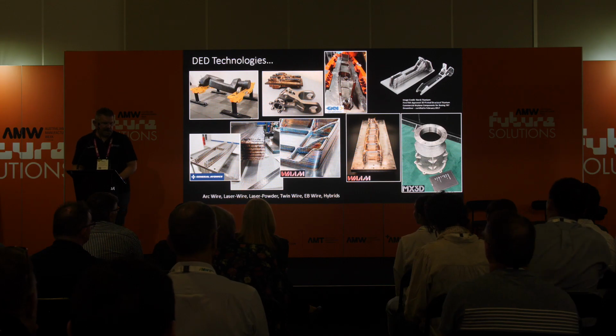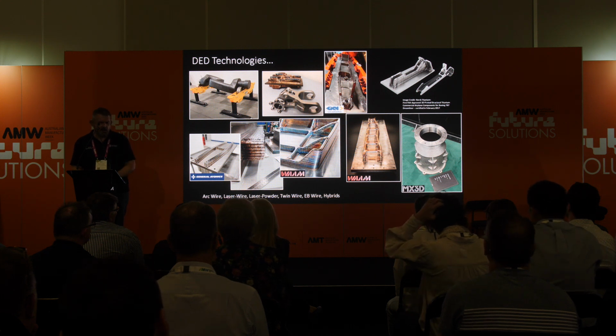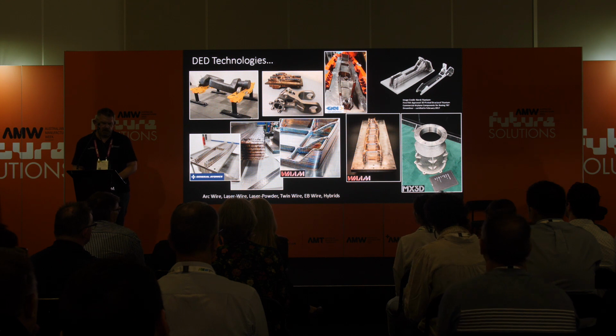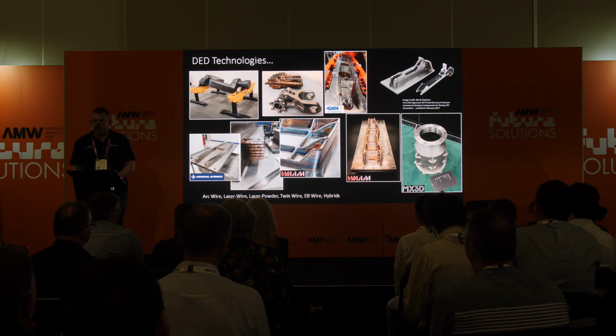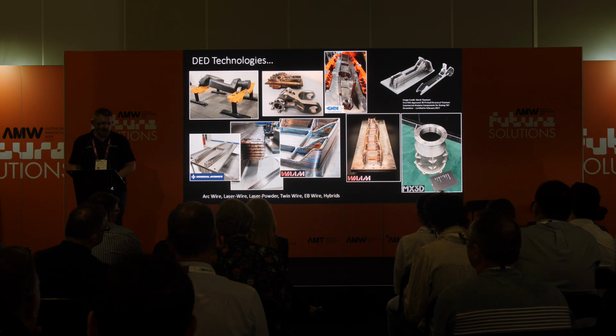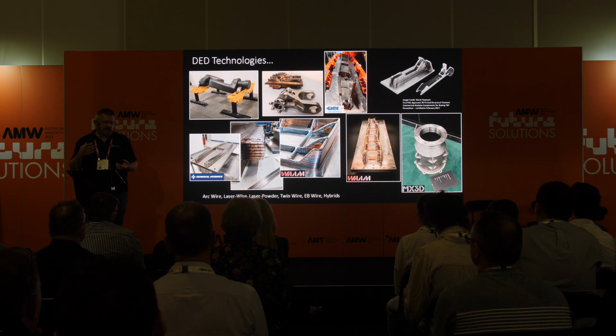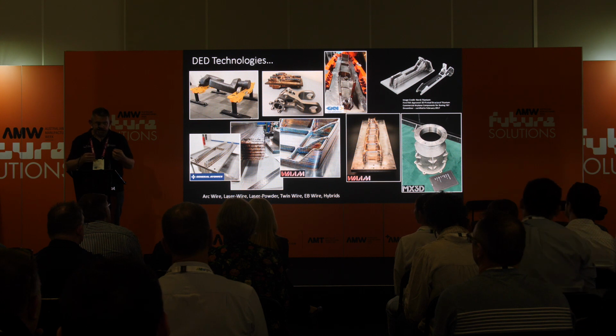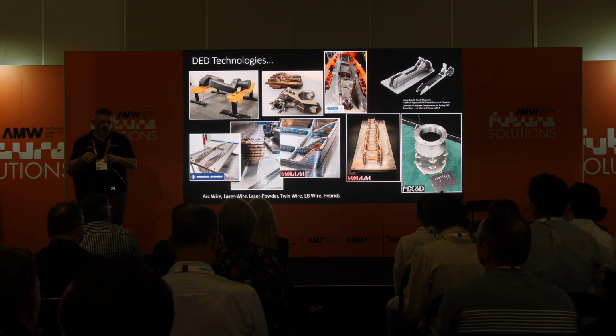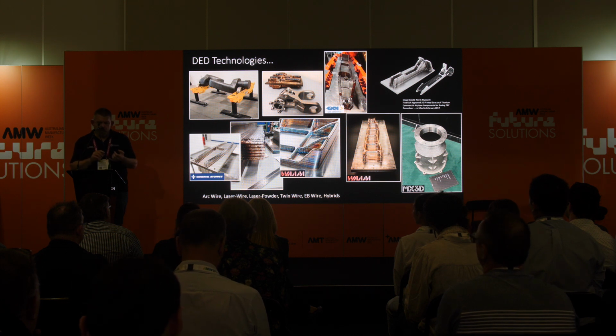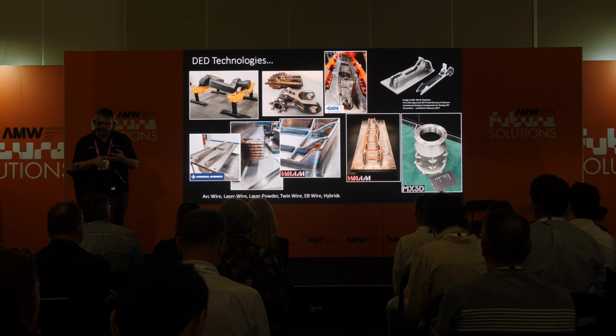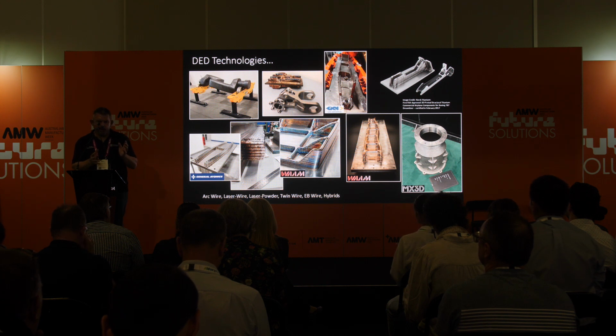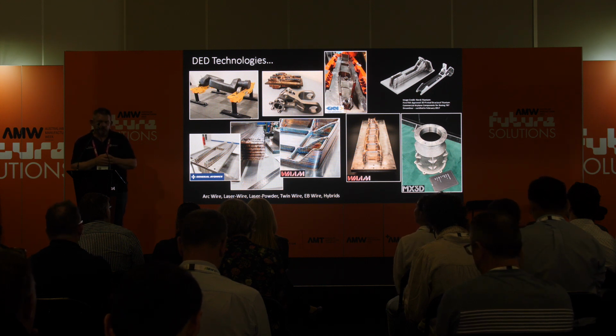A couple of other exemplars there, titanium material, and in the lower right, that's an Inconel material, again from our Formnext show a year or so ago. What you get out of that picture is scale. What you don't necessarily get out of that picture is the propensity for distortion. So we have this challenge of managing the part evolution and managing the thermal distortion, managing the shrink cracking, managing the changes. So back to the monitoring systems, the imaging systems, the measurement systems, and we're not far away from closed loop control. So we can figure out a process going off nominal, and we can actually make a correction on the fly, so that when we get to the end, we've actually got the product that we intended.